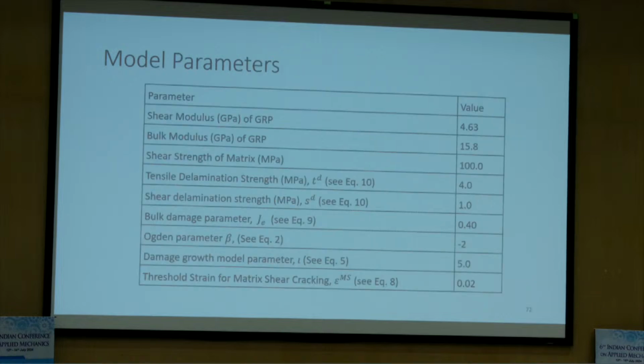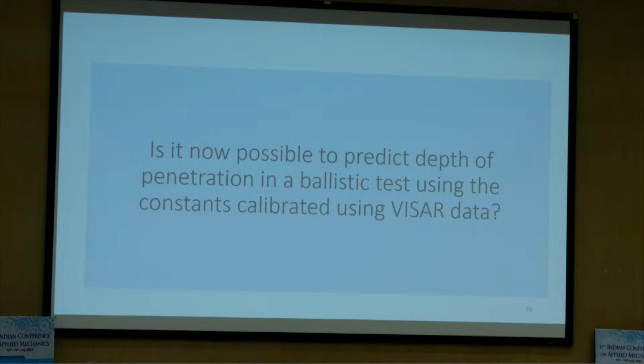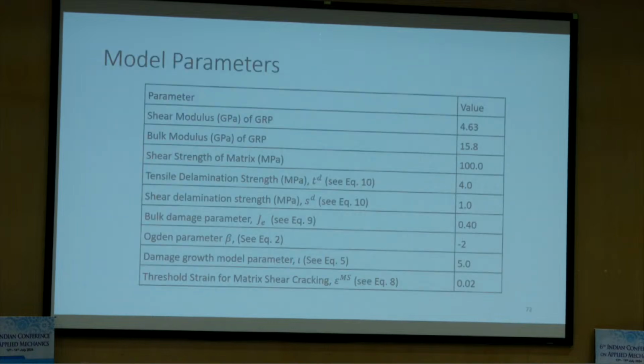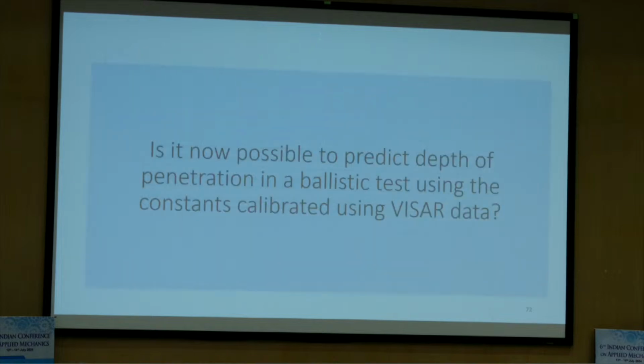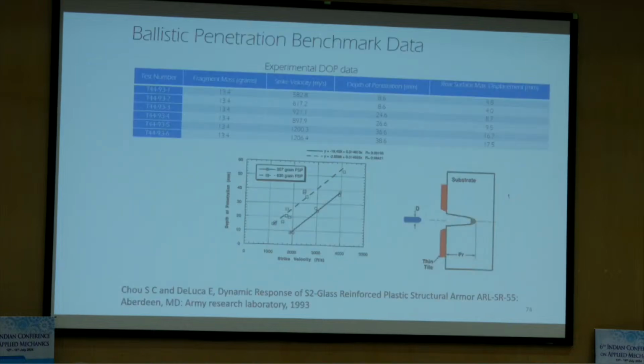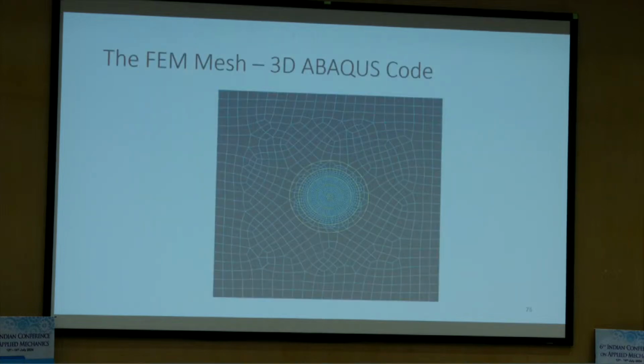So then we thought, okay, we got all the parameters, and how about using the same parameters, which we calibrated using the plate impact test? Now let's see, can we predict depth of penetration in a ballistic test? That is the ballistic test where the bullet stops inside the target, and you can measure how much depth the projectile penetrated. And we have data for that, and we came up with a silly design.